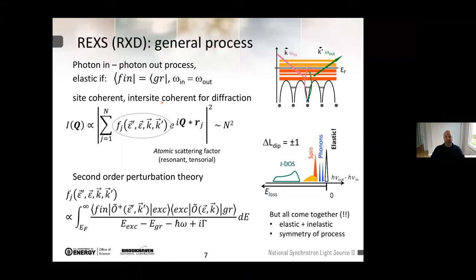So in general, these are the only two equations that I have in my talk, just to say that we measure an intensity at the detector that is written exactly identical to what you are used to in standard diffraction, except that now the atomic scattering factor does not depend only on the modulus of Q, but, given this process that is projecting some wave function, intrinsically tensorial, you depend on the incoming and outgoing wave vector of the light and their polarization. Second order perturbation theory helps us in understanding how to do it. And essentially, as you can imagine, it's a standard